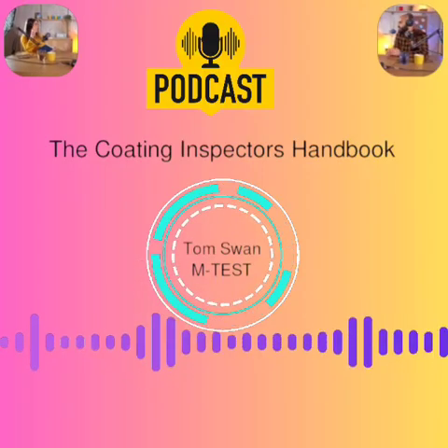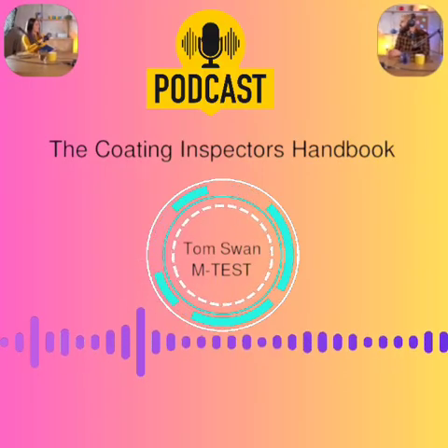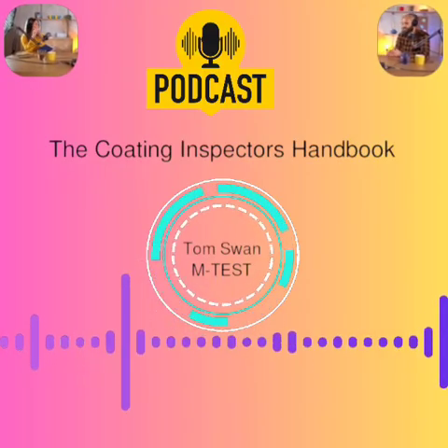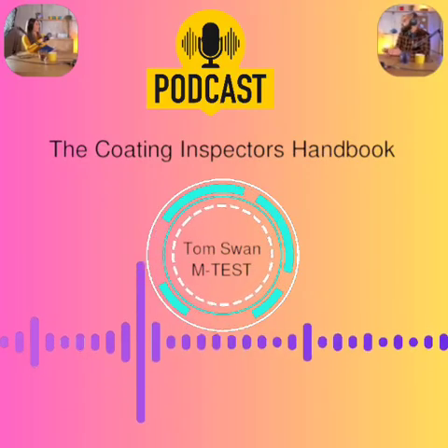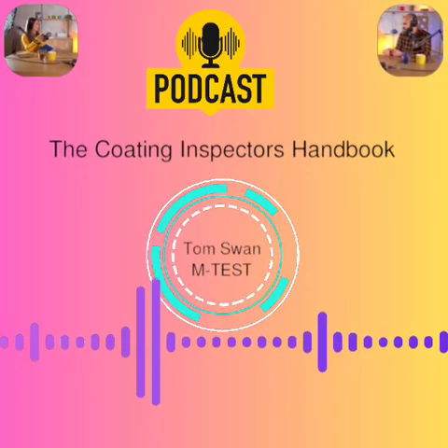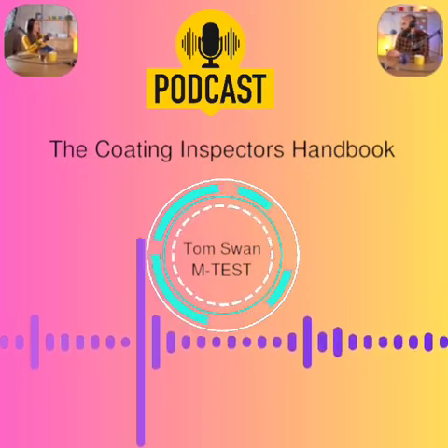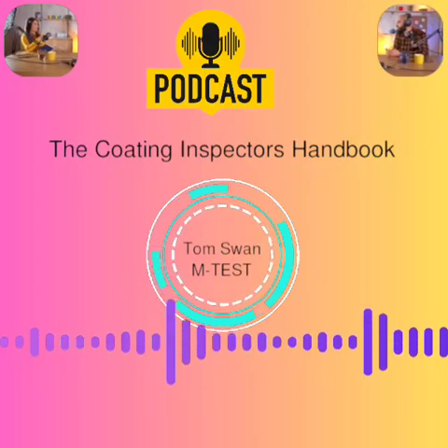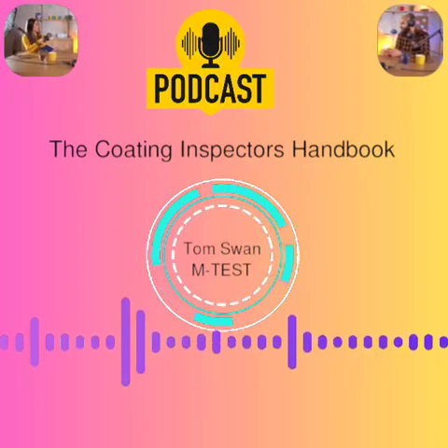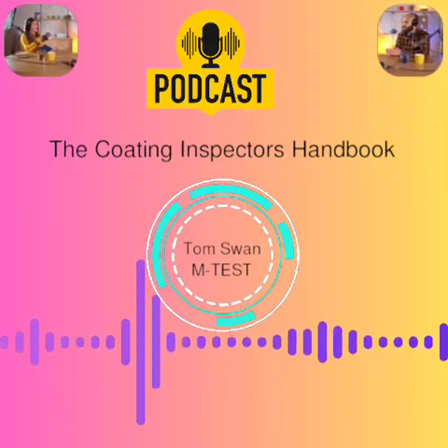Tape adhesion first. ASTM D3359, ISO 2409. Quick check if adhesion is generally adequate, designed for steel, maybe less consistent elsewhere. Not for measuring high adhesion levels, just checking if there's a basic bond. When would you do it? Suspect application issues, bad prep, missed overcoat window, checking old paint before recoating, failure analysis.